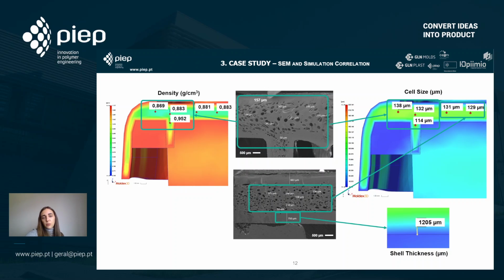So we wanted to confirm this analysis, and we went on to another section of the part. In this case, what we could see was that the shell, in the case of cell size, is higher. The simulation can, in fact, replicate that there will be a higher shell in this section, and it can also create a tendency in the density of the part. However, for the cell sizes, once again, it could not at all replicate. It is uniform throughout the core of the part, which is not the case for the experiments we had.